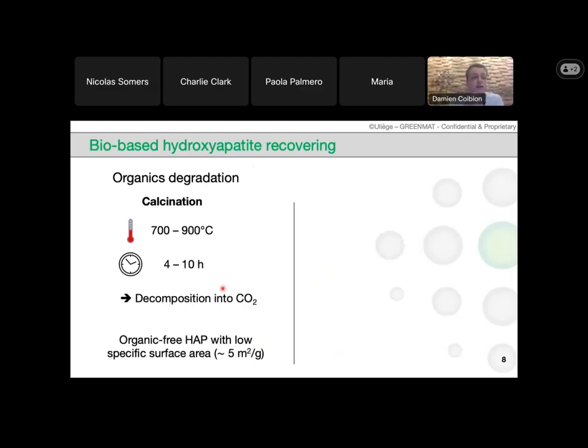The first one is the conventional technique, which is calcination, where the organic molecules are decomposed into CO2. In the literature, we can find temperatures between 700 and 900 degrees C, and the dwelling times are most often between 4 and 10 hours. So we can recover an organic-free hydroxyapatite with a quite low specific surface area, close to 5 square meters per gram.